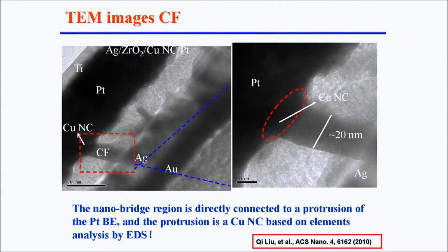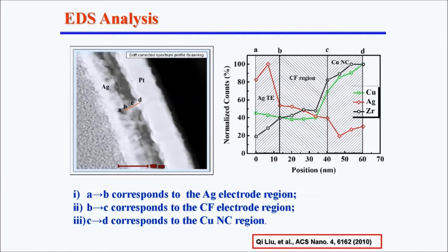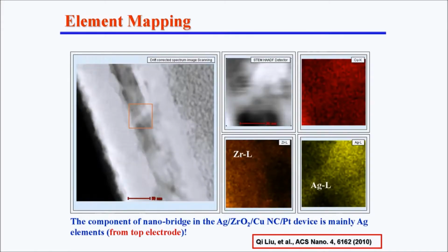Also, furthermore, we analyzed the composition of this filament. This is the EDS analysis. We can see this filament is silver. So why is it silver? Because one electrode became silver. Usually for TEM the host is a copper grid, so if you use copper as a baseline, the signal is very strong. Also, in the further mapping, we can clearly see the copper is very uniform. For zirconium, also very uniform. Only in silver can you see this electrode, this filament. That totally gives the evidence. This filament can be controlled by the strong electric field. Also, the filament composition is very clearly shown here.